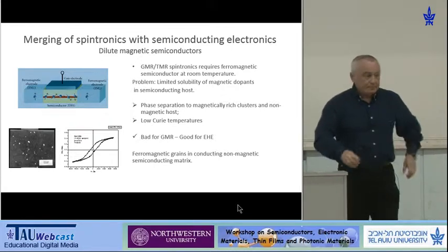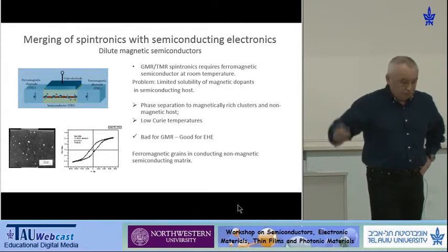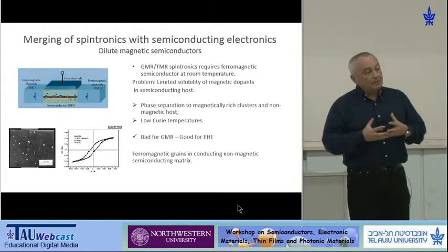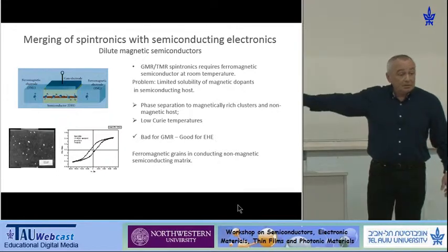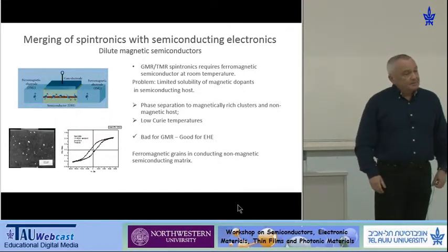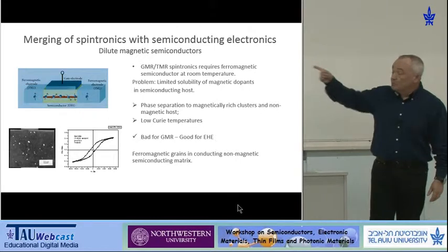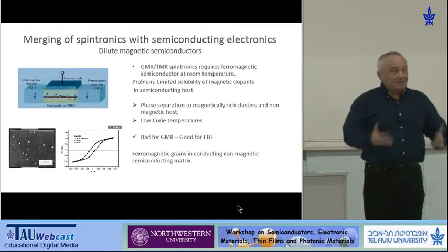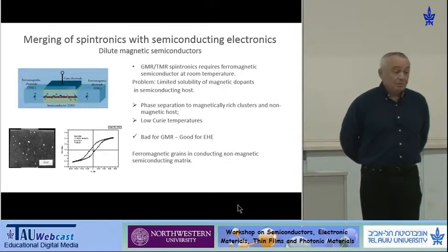Yeah. Just a side note, in our indium antimonide, we see 550 K, T sub C. That's fine. This is absolutely fine, because again, the clusters which are manganese rich, or depending on what you put inside, can have a Curie temperature at very high temperatures. So the moment we're below the Curie temperature and below the blocking temperature of the cluster, you will get this type of response. But it still doesn't mean that the material is a ferromagnet. But the matrix still may be paramagnetic. It can be, true. True. True.